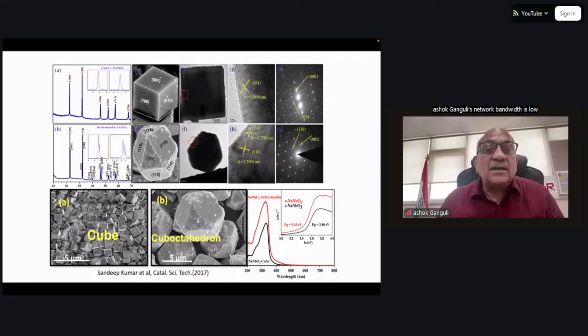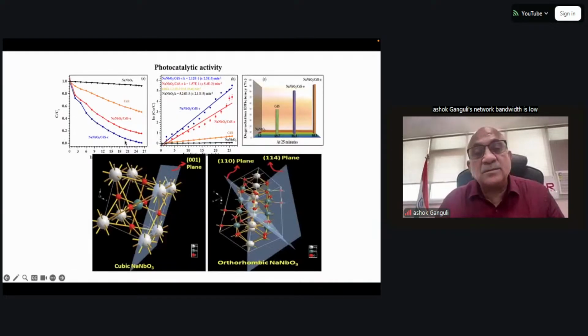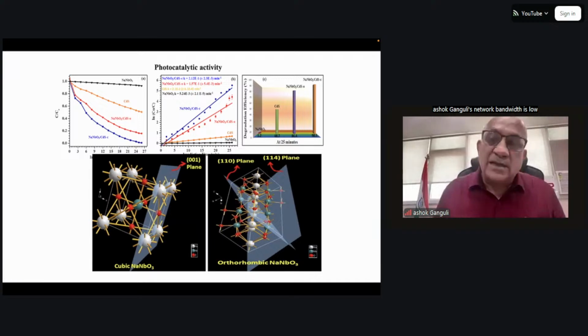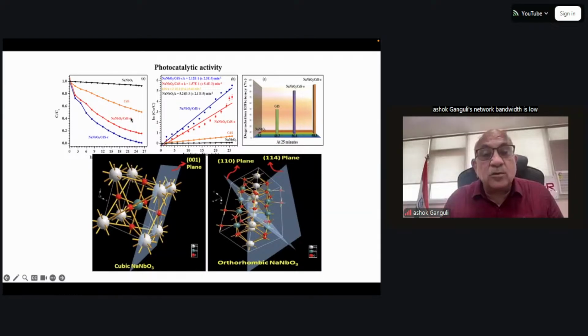And once you put on top of that, that is cadmium sulfide. So the one which has got the cubic one shows rapid degradation of the dye. That means the reducing power is more, which means electrons are reaching there faster, and which means electron and hole are not recombining. So this is a better photoelectrochemical catalyst compared to the other orthorhombic shape, which is formed by the nanoparticles having the cuboctahedral morphology. We can do some calculations and explain why this happens based on the atoms on the surfaces which are involved in the cubic structure and the orthorhombic structure.